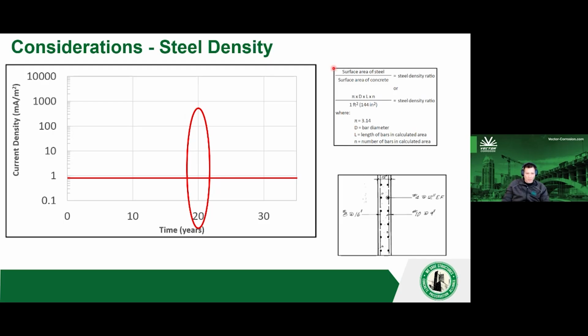Because the thing that actually corrodes in the structure is not the steel core, it's only the surface area that interacts with the concrete. So that's what we're trying to protect, the amount of steel surface area. We want to protect that with zinc surface area. And there needs to be a proportional amount to get the life we're looking for. So to figure out the steel density overall, you're taking every bar, every piece of exposed steel that you can, longitudinal, transverse, both directions. If there's 2 layers, you take both, add them all up, do the proper calculation. In this case, the steel density was 0.98.